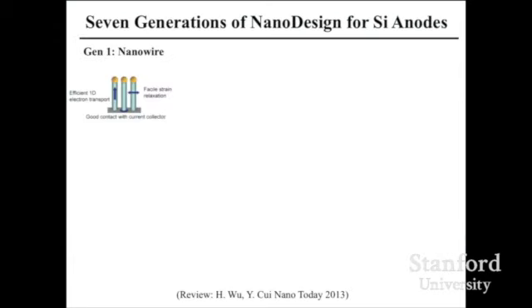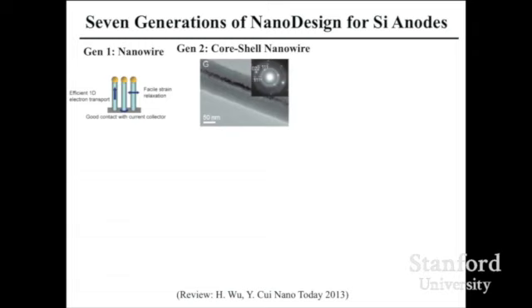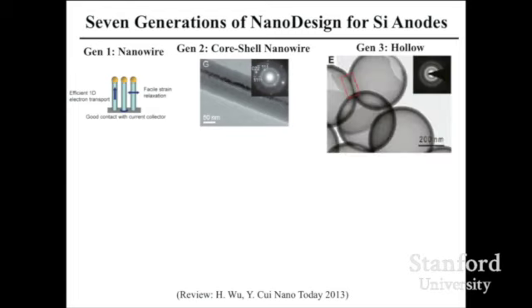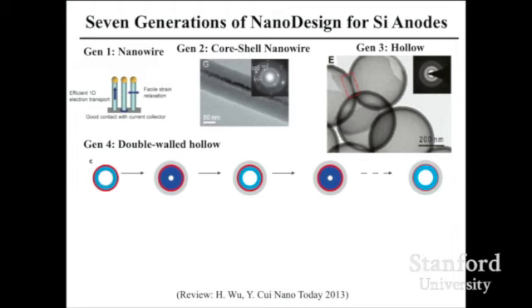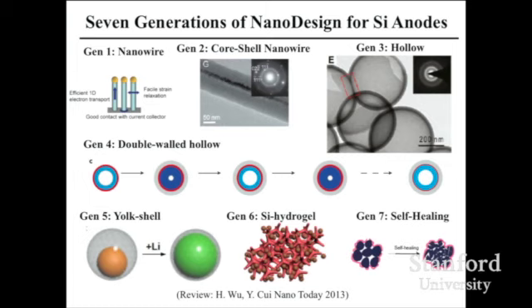So through several years of understanding, we started from silicon nanowires. We moved on to generation 2, making core-shell wires, having a stable core and amorphous shell, to maintain mechanical support and keep moving electrons more efficiently. That improved the batteries. We also went to the hollow nanoparticle structure, using the interior surface to relax the strain without breaking. So it's improving year by year. And then we went to the double wall hollow structure. I will tell you why we want to go to double wall. Later we went to yolk-shell, the silicon hydrogel, and then self-healing. Now it's generation 7. And this month we are going to have generation 8 coming out, but I'm not ready to release this yet.